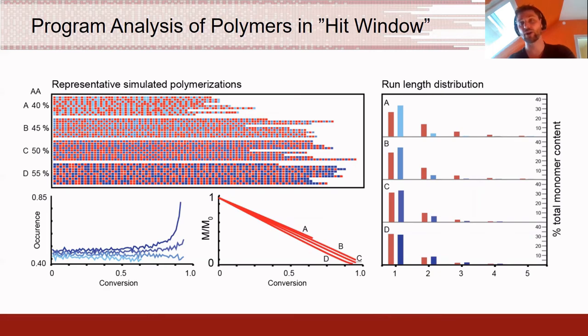So if you want to try a 40 to maybe push it to a 30 to 70% range of acrylic acid, well, you can stop it earlier and not have that much composition drift, and have a fairly alternating copolymer, but with variation that is forced upon the system by simply not having equal ratios of monomers.